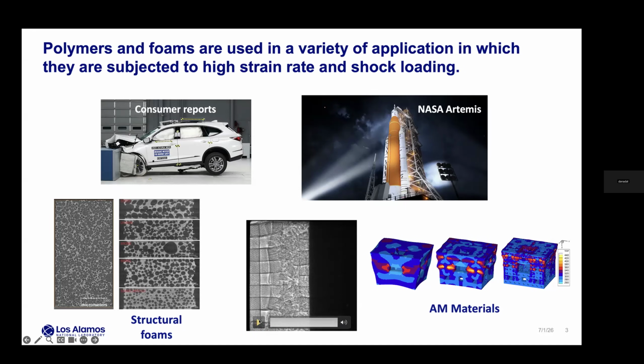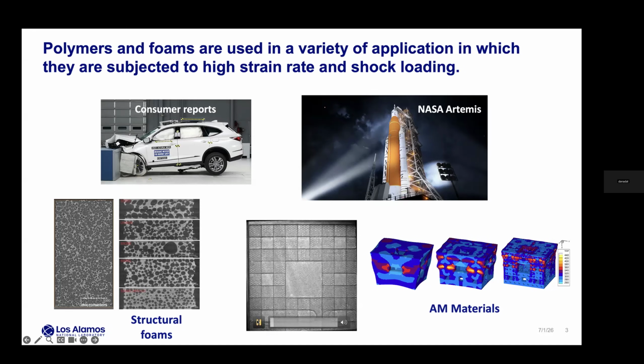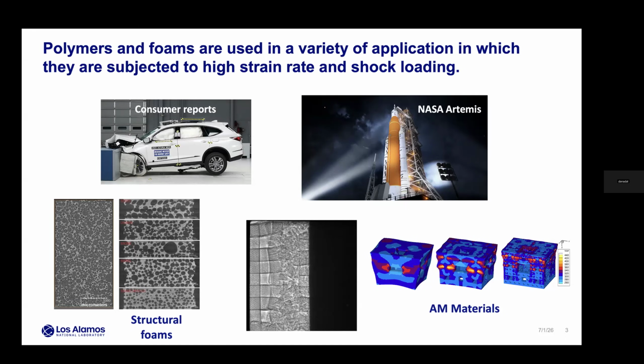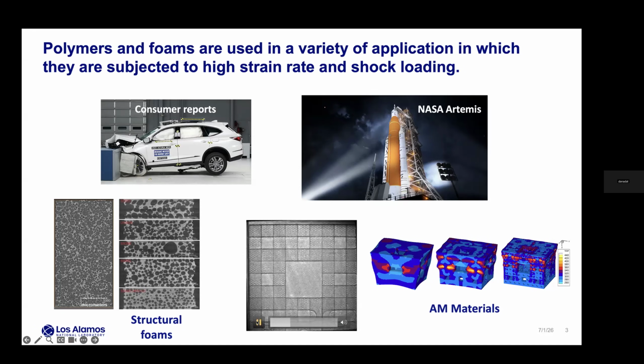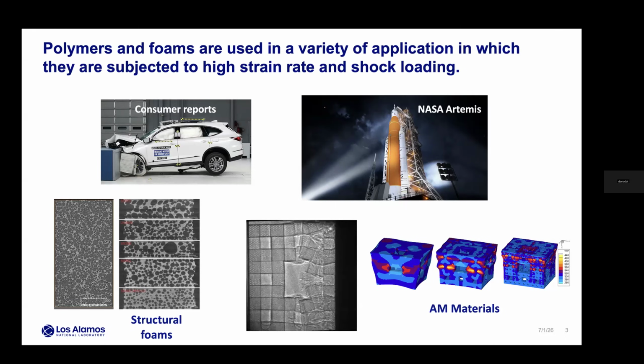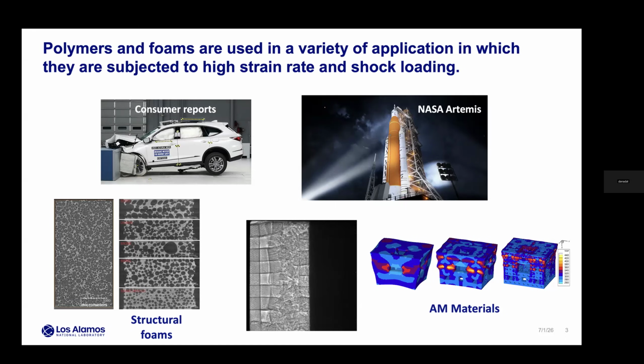And then over here, I'll rerun this movie. We had an LDRD project a few years ago, actually designing the properties into the material. So this is an example of a fractal polymer structure that we 3D printed using 2-photon polymerization. And using this fractal structure, and I referred to these in my paper as interface dominated materials, we showed that we could reduce the shock going through the material by 10-fold over just a millimeter or two in the material. So these are also potentially applicable to the warfighter in terms of helmet materials, and these were in particular looking at vehicle protection.